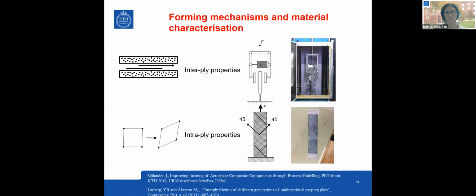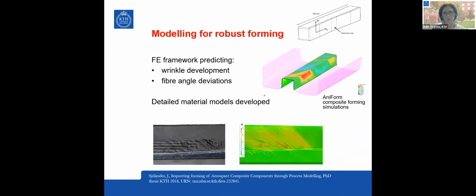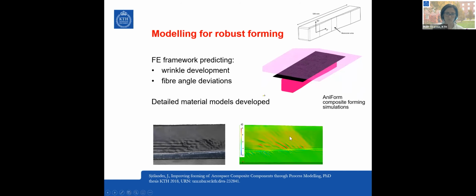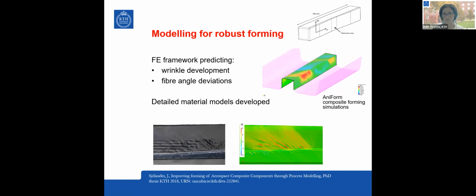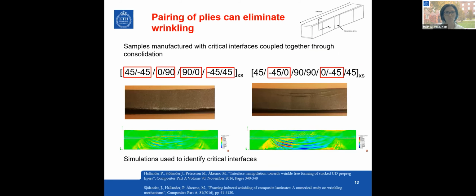Based on this, we have started looking into the forming mechanism, trying to understand why this is happening. We have mainly looked at interply properties, the properties in between the layers, and how the material shears. We developed a material model and put that into forming codes. So we have used the AniForm composite forming simulation tools. We have developed detailed material models and been able to predict wrinkles, as you can see here, the very small wrinkles on the inner side. We can see them as stress levels in the simulations, but also see exactly which fiber angles come out after forming.